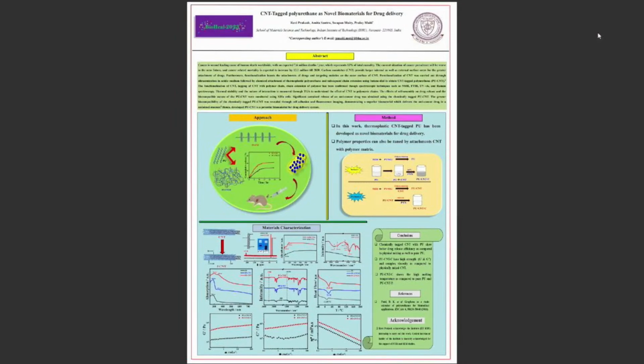We also studied the rheology: the gel strength of the CNT tagged polyurethane is higher compared to the physical mixing and pure polymer, and at higher shear rates, the CNT tagged polymer shows higher viscosity compared to the physical mixing. We concluded that the chemically tagged CNT shows higher sustained release compared to the physical mixing, and the polymeric properties are also tuned with the CNT and with the grafting of the polyurethane. Thank you.